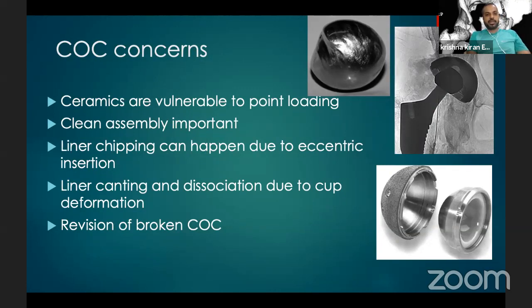So you must have clean assembly of both the liner and the femoral head onto the trunnion, which may not always be possible intraoperatively. If you eccentrically insert the liner, it will break. So you must be careful when inserting it. There are two types of liner tapers available: a 10-degree taper and an 18-degree taper. The 10-degree is relatively easier to insert. But if we are using an 18-degree taper like the Johnson & Johnson taper, one needs to be extra careful while inserting it, because a tendency to eccentrically insert the liner can lead to liner chipping and fracture.